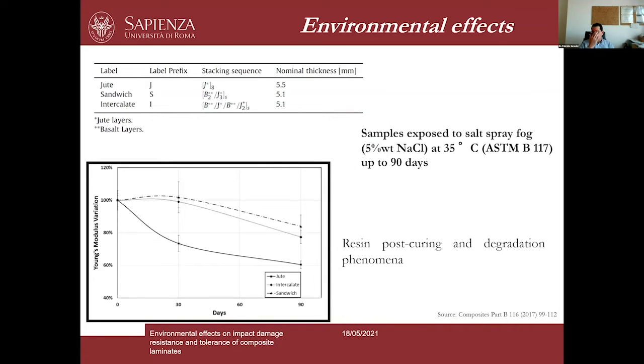And this is something that we have investigated. In this case, we actually considered jute fiber composites. And of course, in an attempt to reduce, for example, the effects of environmental aging, we tried to solve this issue by hybridization. So basically, what we did is to hybridize jute fibers with basalt fibers. Basalt fibers, in this case, are natural fibers of mineral origin, but they show mechanical properties which are comparable with the properties of glass fibers.